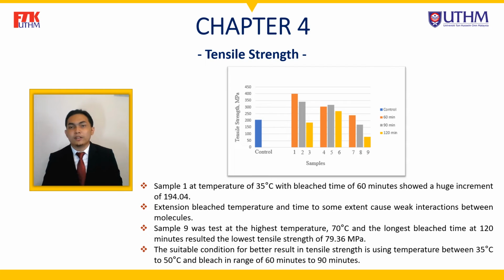There are reasons which can explain the result. The deterioration of tensile strength is caused by extended bleach temperature and time to some extent, which results in interaction between molecules. Hence, the tensile strength decreases when the treated fiber is over 50 degrees Celsius. The longer the bleaching time and the higher the temperature, the lower the tensile strength. Sample 9 was tested at the highest temperature, 70 degrees, and the longest bleach time, 120 minutes, and resulted in the lowest tensile strength of 79.36 MPa.